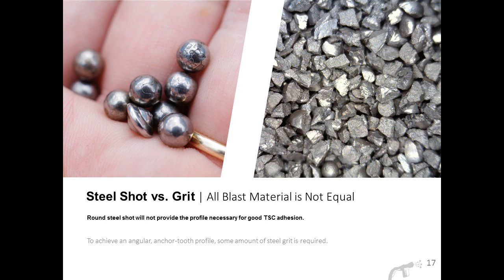So there is a difference between steel shot and steel grit. All blast material really isn't the same, and it's important to make that distinction when we're talking about metallizing. Abrasive blast cleaning is a really important step to treating steel before applying any coating. It's generally accepted that blasting is the most important factor to the success of any corrosion protection system. Typically, blast cleaning removes any of the mill scale, rust, oil, grease, and other contaminants that the steel may accumulate through the production and transportation process.